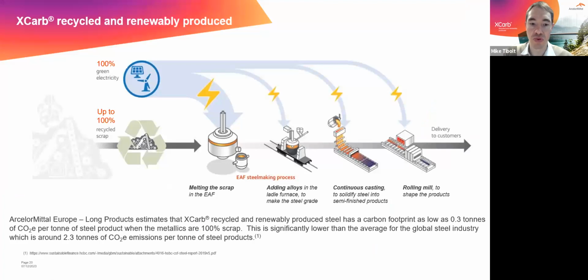Recycled and renewably produced means that we are using 100% green electricity, mainly from solar and wind energy, to power our production lines, so the melting of the scrap in the arc furnace, the alloying phase, and also the rolling mill, and to use up to 100% recycled scrap. By doing so, we can reduce the CO2 footprint of our product from a global average of steel production of 2.3 tons of CO2 per ton of steel product, down to between 0.3 and 0.4 tons of CO2 per ton of steel product. Now, how exactly does this work? This is shown on the next slide.